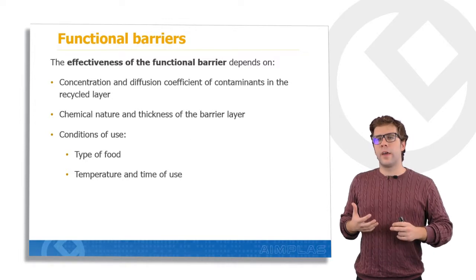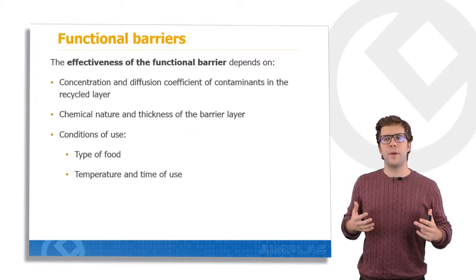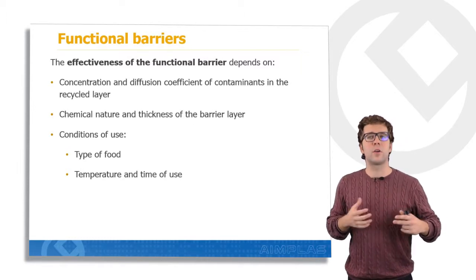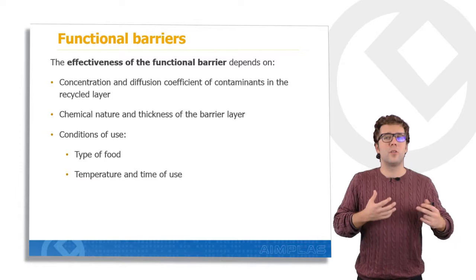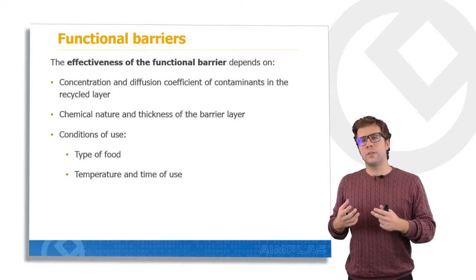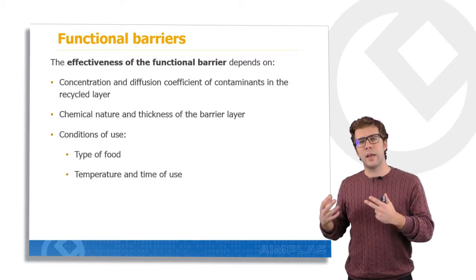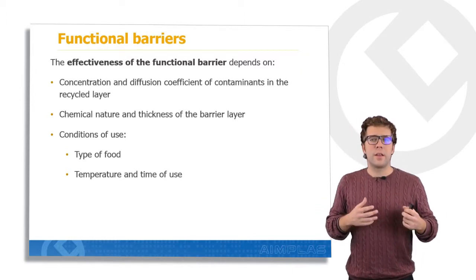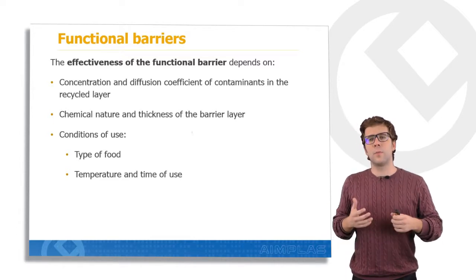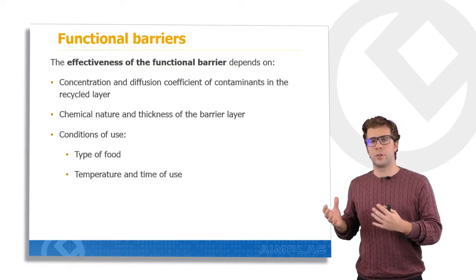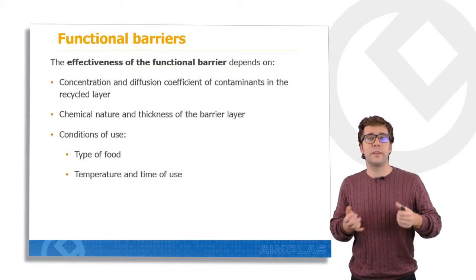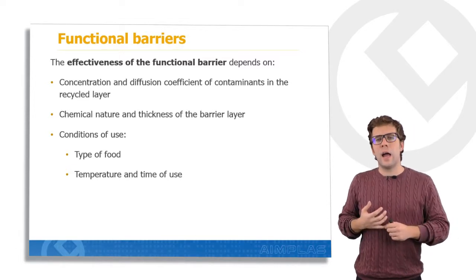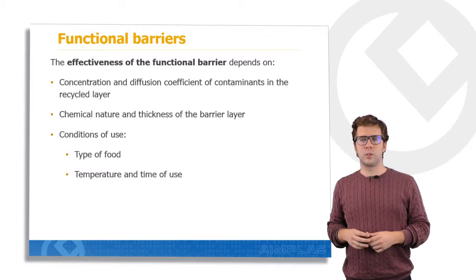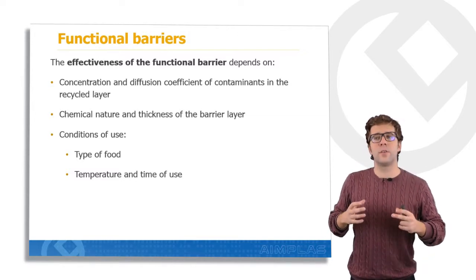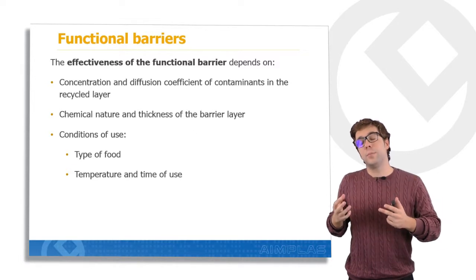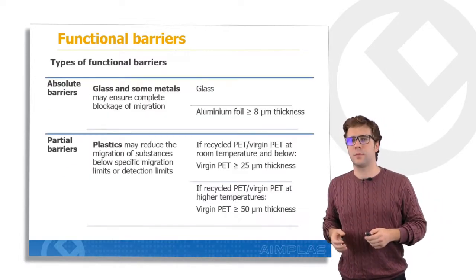Moreover, the effectiveness of the functional barrier depends on several parameters: on the recycled layer, on the concentration and the type of contaminants present in this layer. It also depends on the properties of the barrier layer itself, like the chemical nature and thickness of this layer, and it is also very important to define the conditions of use. The migration can also depend on the type of food contained in the packaging and on the temperature and time of use. So the effectiveness of the functional barrier must be demonstrated on a case-by-case basis.